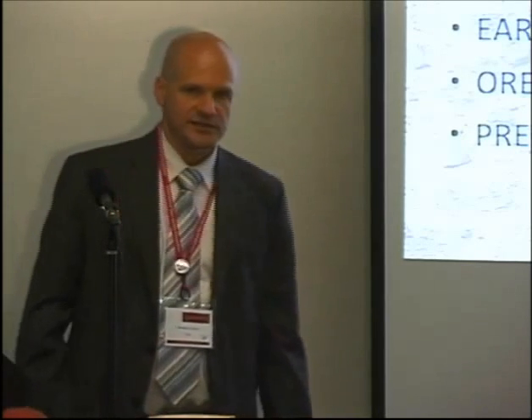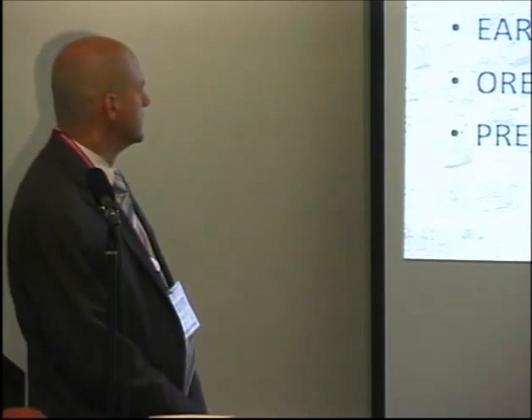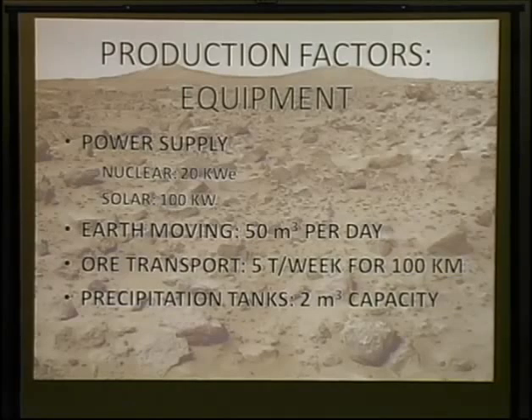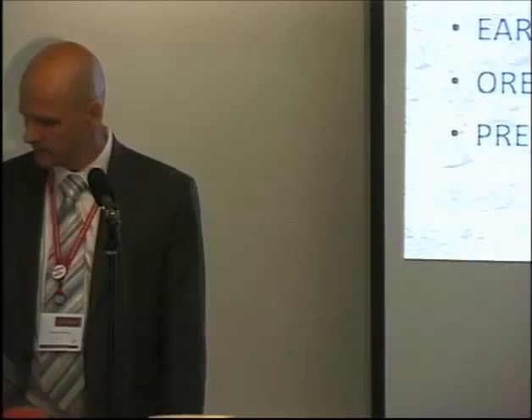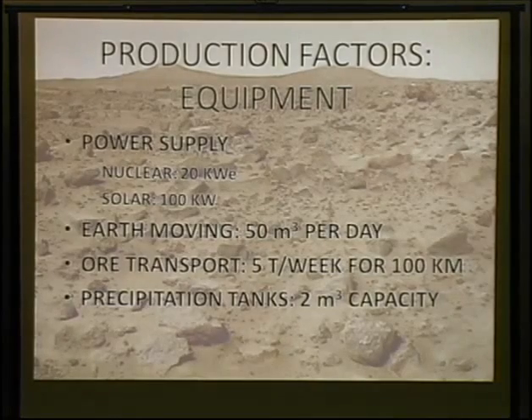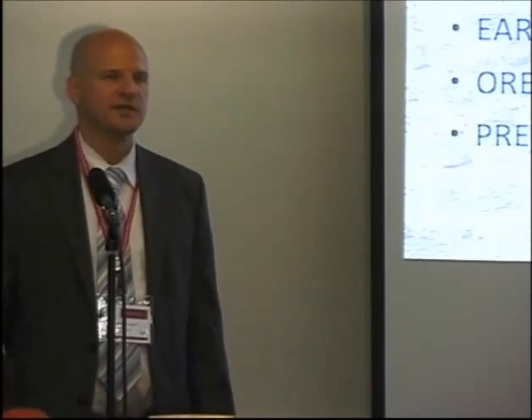And for the reference design I've been working with, which I'll show you later, we'd need the ability to move about 50 cubic meters of regolith per day. And just a rough estimate, I'm thinking of, for ore transport, 5 tons of ore per week over a distance of 100 kilometers should be able to provide our transportation needs. And if we need to use precipitation processes, 2 cubic meters precipitation tank capacity should be more than enough. Yes, to produce 1 ton of magnesium oxide per week, which would give us about 2 tons of cement.